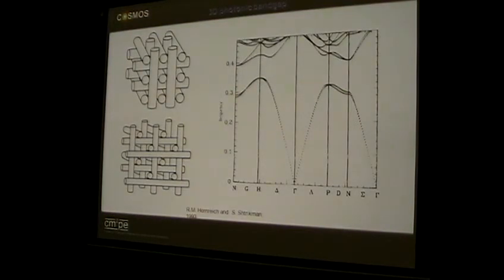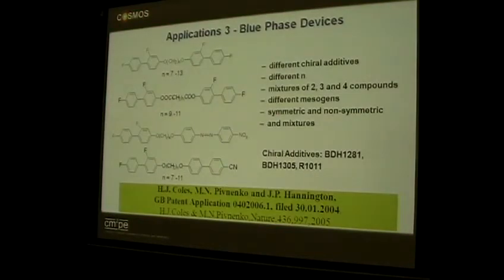That's just another depiction of the cubes and therefore the disclinations that occur. So again, we use bimesogens, and there's a primary reason for this: these materials, as I've just told you, have very high flexoelectric coefficients. That means that if the system is deformed, it will have a transverse dipole, or some transverse polarization across the director direction. That's the key to the flexoelectricity. So we're using materials that can deform in shape, the flexoelectric effect, to give you, as you'll see, a wide temperature blue phase.